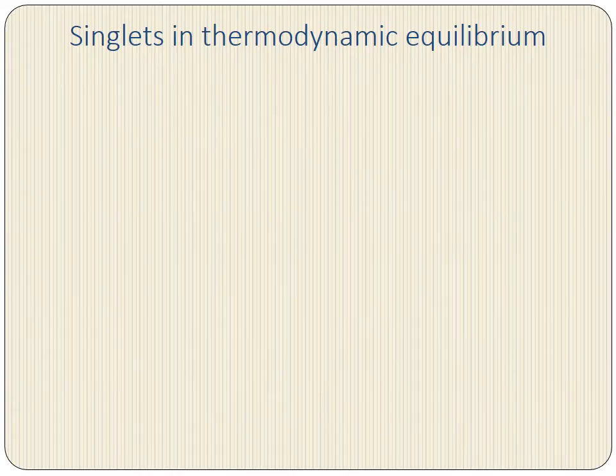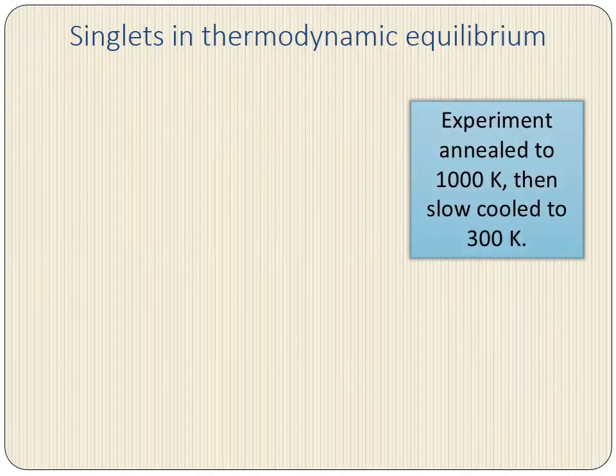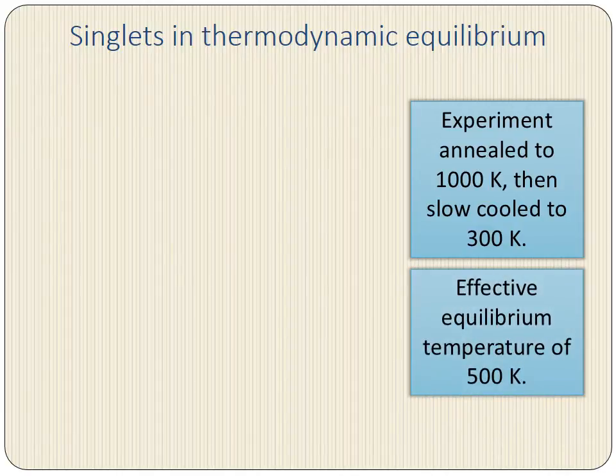Well, the last ingredient that we need is the temperature for our model. We recall again that the actual protocol for the experiment was to anneal to 1000 Kelvin and then slow cool it down to room temperature. So our value of temperature should lie somewhere in between these two values. However, we can't actually assume that at any point in the experiment the singlet formation truly reached thermodynamic equilibrium. So our temperature is going to be effective. Here, we're going to choose the value of 500 Kelvin. However, we should note that this is in the end a tunable parameter.